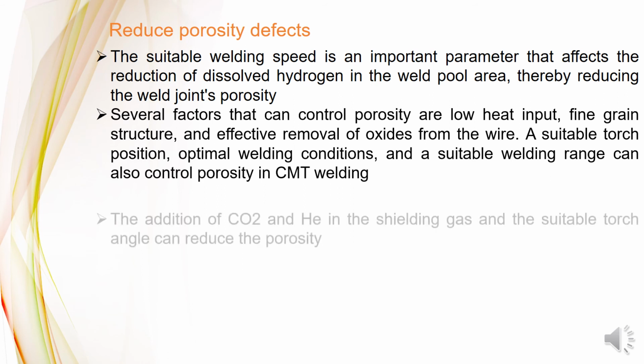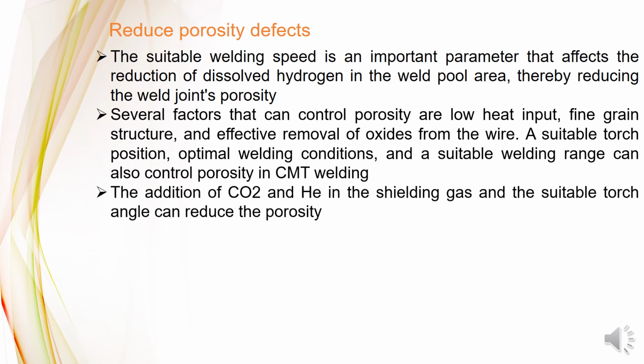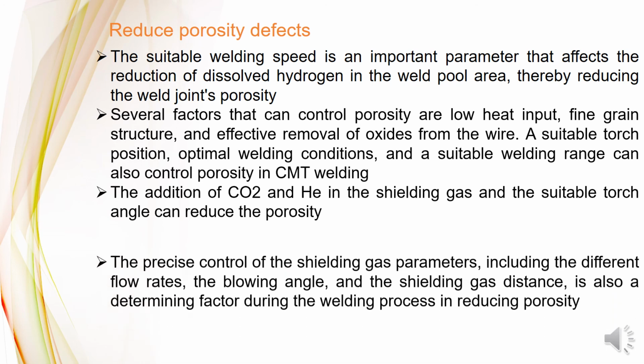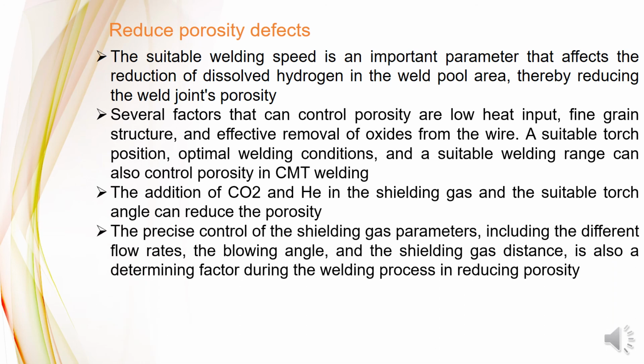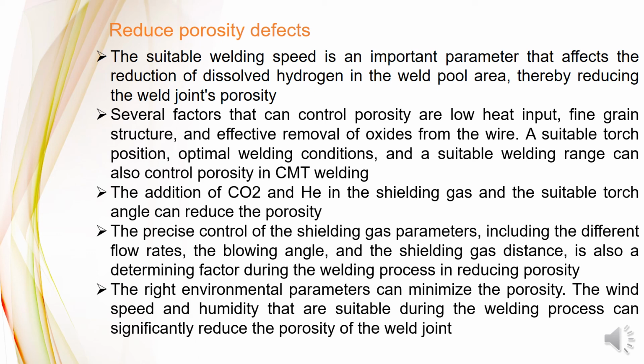The addition of CO2 and He in the shielding gas and the suitable torch angle can reduce the porosity. The precise control of the shielding gas parameters, including the flow rate, the blowing angle, and the shielding gas distance, is also a determining factor during the welding process in reducing porosity. The right environmental parameters can minimize the porosity. The wind speed and humidity that are suitable during the welding process can significantly reduce the porosity of the weld joint.